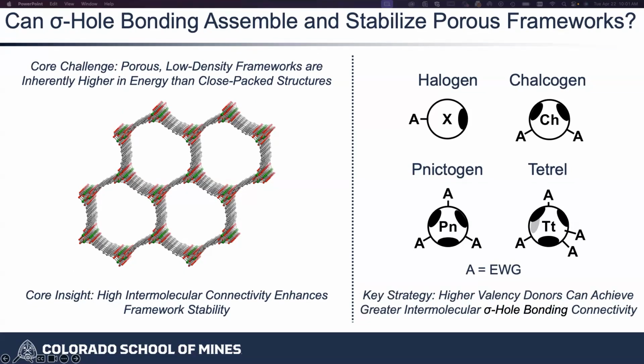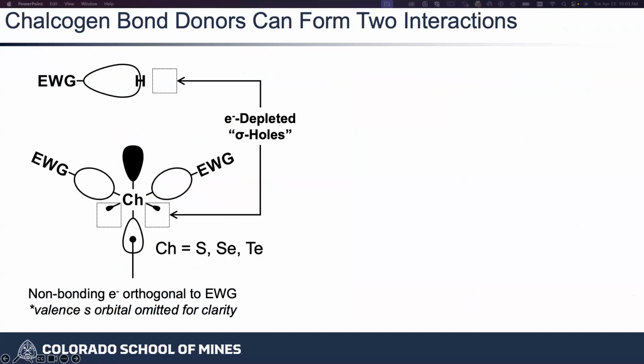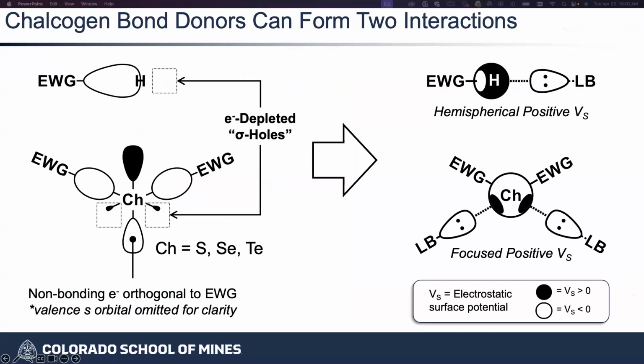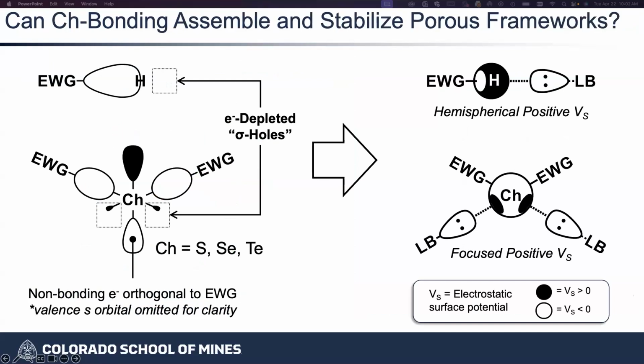All right. And so although halogen bonding was definitely the most well understood interaction at the time, because there's only 1 of these holes, we decided to go next door to the chalcogens where there's 2, theoretically forming more interactions per unit volume, creating more architectural soundness. And so just to continue this description, if we have a chalcogen, sulfur, selenium and tellurium as well, that we talk about primarily, you have 2 electron withdrawing groups, and you can theoretically form 2 of these interactions on a single atom. Okay, so the question became, can we build materials out of chalcogen bonding specifically?